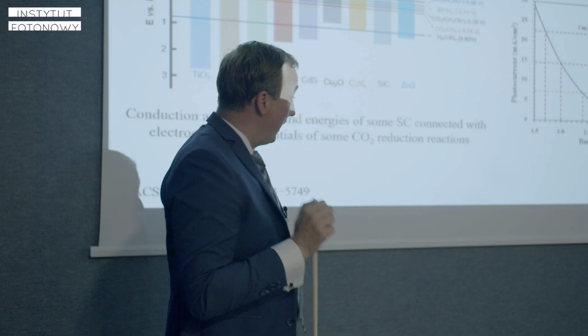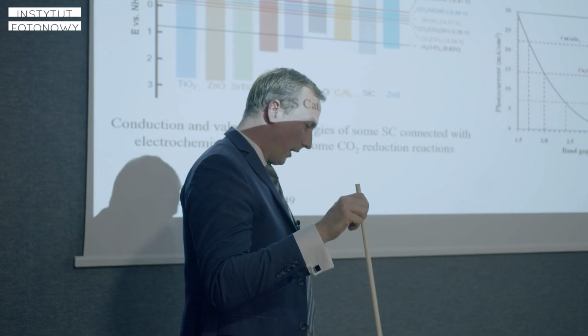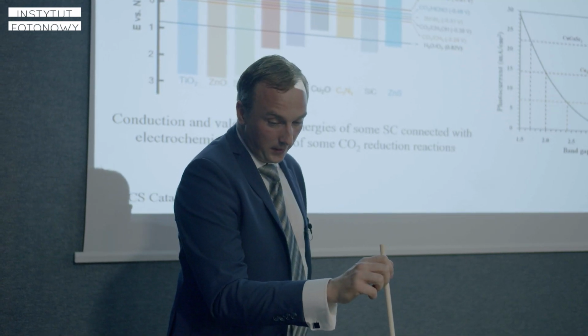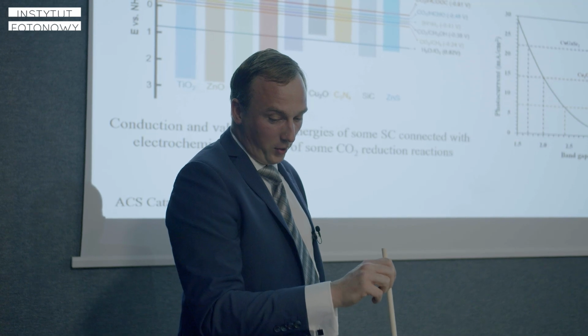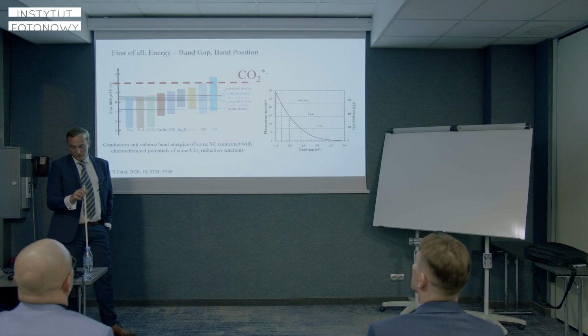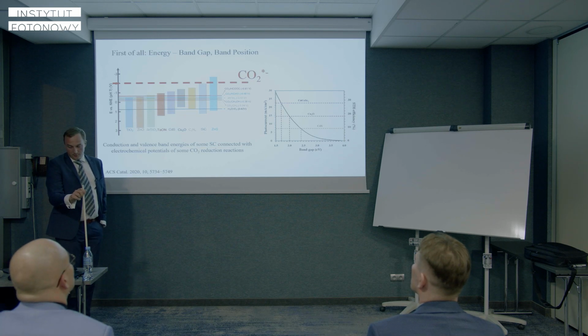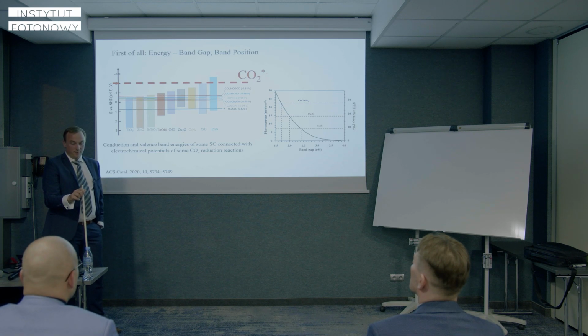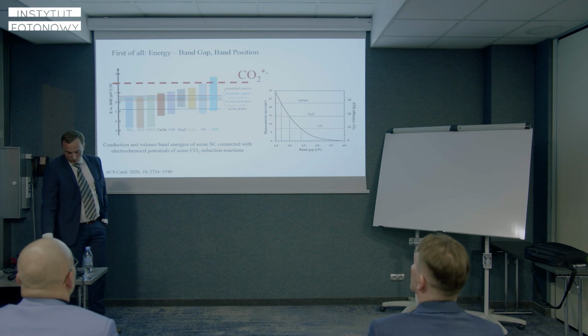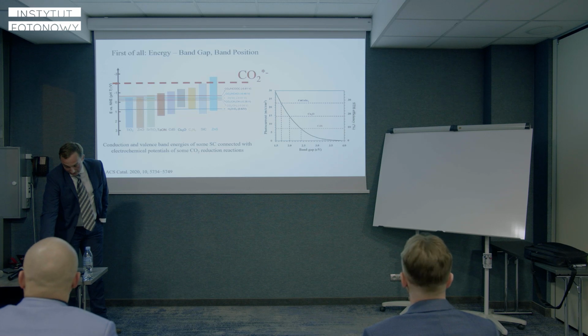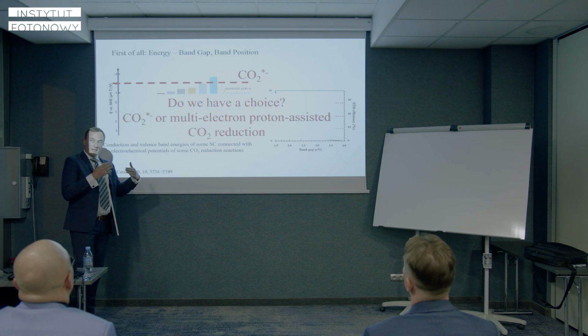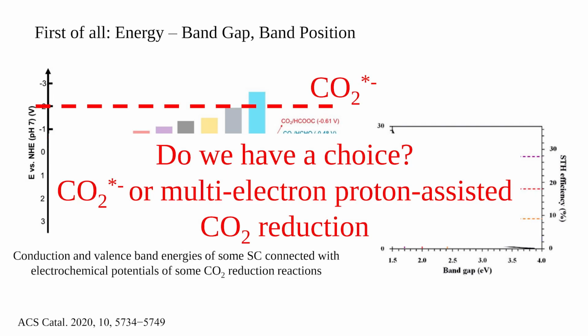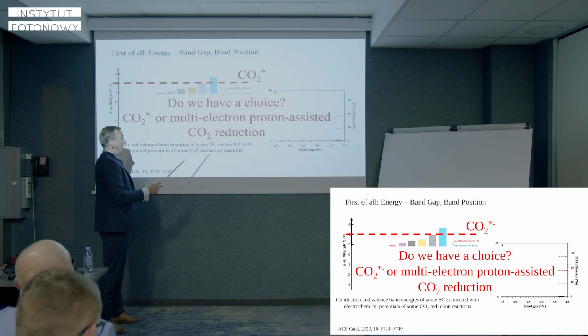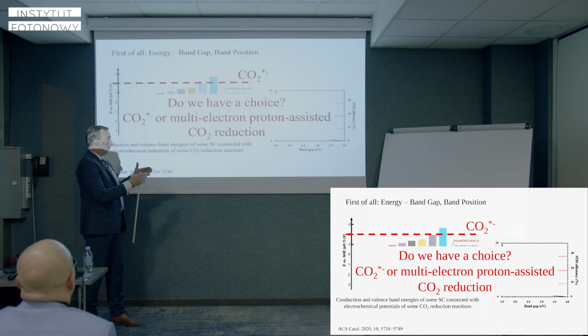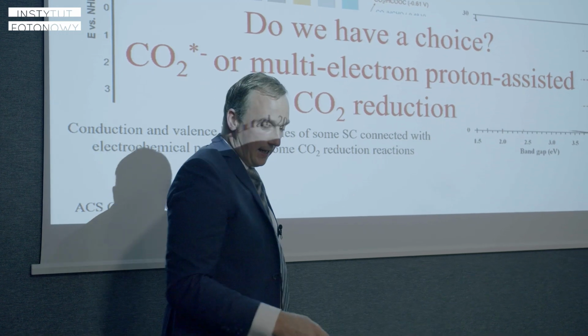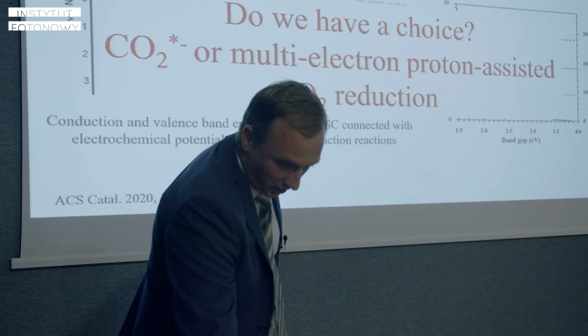So we want to have carbon dioxide reduction using a multi-electron system. This multi-electron proton-assisted carbon dioxide photoreduction is another studied mechanism, as it presents a much more favorable redox potential. However, CO2 reduction to the same product when we use multi-electron reduction may proceed via different and competing pathways. So we have a choice. We can reduce carbon dioxide using a CO2 radical anion, which will be much more selective, or more efficient but not as selective multi-electron pathways. So this is the beginning of my talk about the photoreduction.